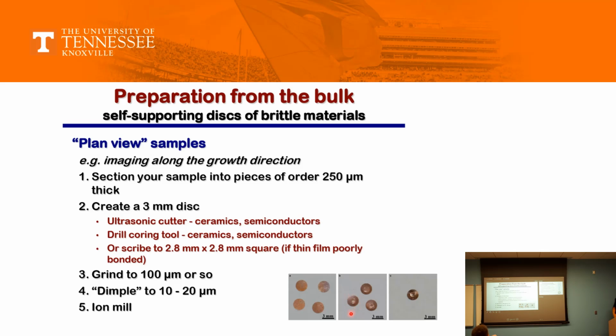Then you put jets of your chemical on it, and we have an electropolisher here that creates a hole. You analyze your sample at the boundary of the hole, because we assume that just at the boundary there are some thin edges left over, which contain all the information about the sample. You could call it a very primitive technique, but we have no choice, because as someone told me in the last class, with FIB we create a lot of damage. So we need other mechanical or chemical polishing methods to create samples.